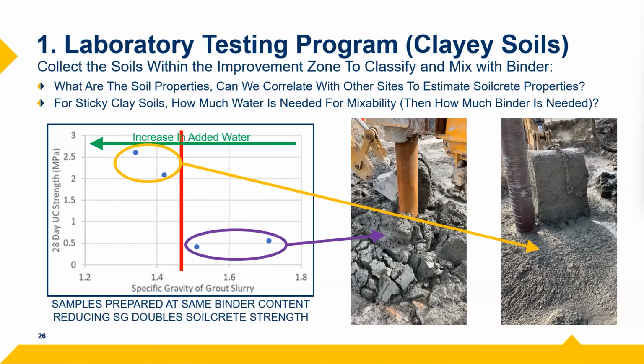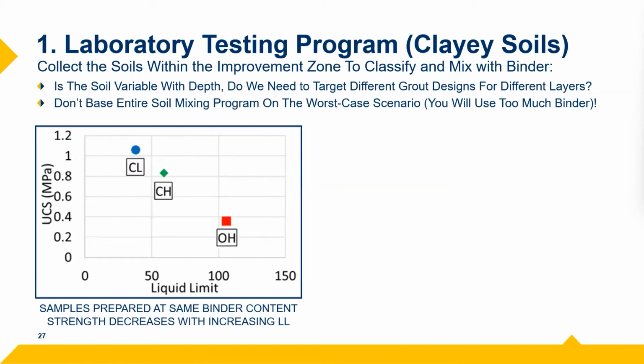And unfortunately, this breaking point of specific gravity or amount of moisture is different for every soil, for every type of geology that we're in. So running these laboratory testing programs is very important, especially when we get to soil zones that are highly variable. And this is a project site we worked on where we were mixing through 3 different soil zones, kind of a leaner clay, a more plastic clay, and then an organic clay. And so what we explored is, okay, if we mix each one of these samples with the same grout design, you can see that the strength that we get from our laboratory testing is quite a bit different.